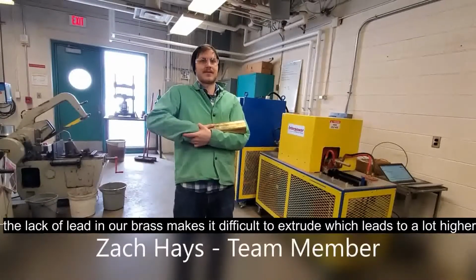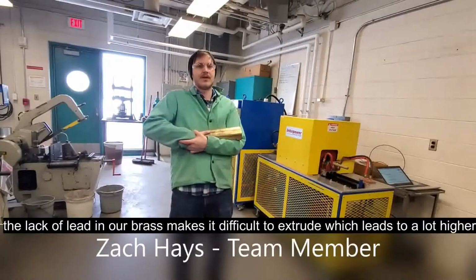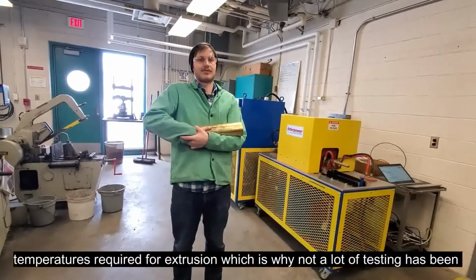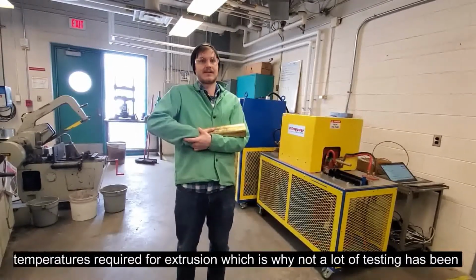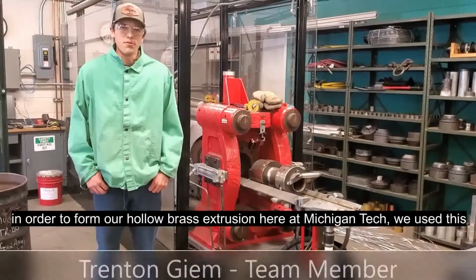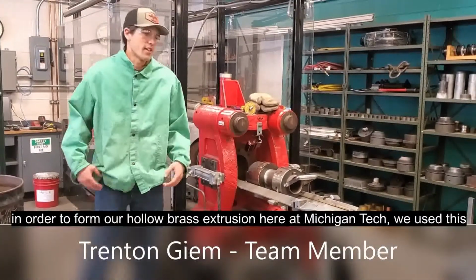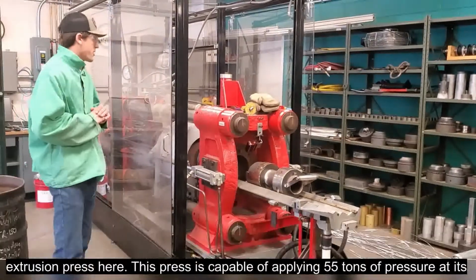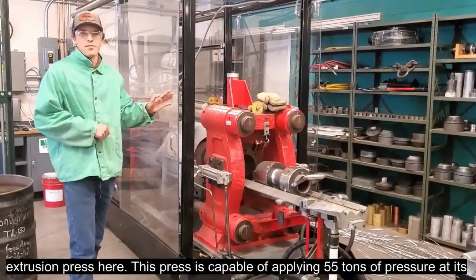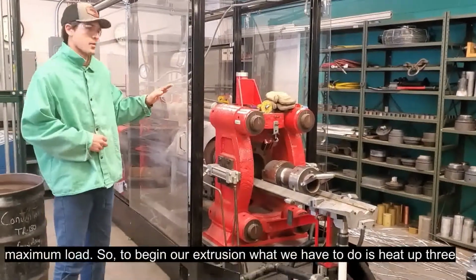The lack of lead in our brass makes it difficult to extrude, which leads to much higher temperatures required for extrusion, which is why not a lot of testing has been done yet. In order to perform our hollow brass extrusion here at Michigan Tech, we use this extrusion press. This press is capable of applying 55 tons of pressure at its maximum load.